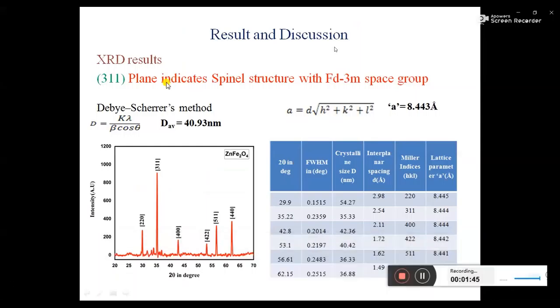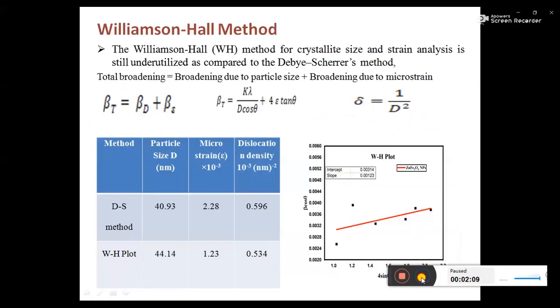The XRD results show that the 311 plane indicates the spinel structure with Fd3m space group. And also we have calculated the particle size by Debye-Scherrer method. The average particle size is about 40.93 nanometer. And also we have calculated the lattice parameter a for the cubic structure, 8.443 angstrom, which matches with the standard JCPDS values. And also we determined the crystallite size and microstrain using the Williamson-Hall method, and we compare it with the Debye-Scherrer method. The particle size for the Debye-Scherrer method is 40.93 nanometer. From the W-H plot, 44.14 nanometer we obtain.